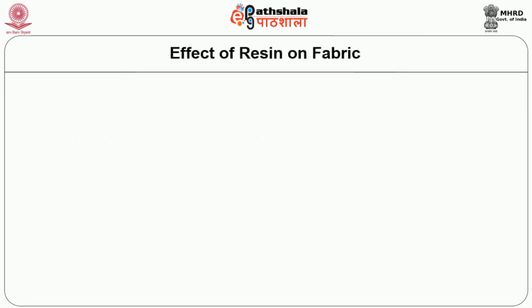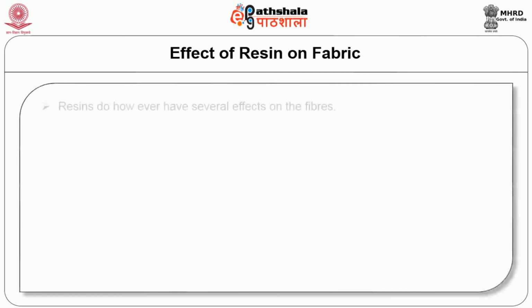The effect of resins on fabric. Resins do, however, have several effects on the fibers. Excessive cross-links cause brittleness, stiffness and harsh feel, giving loss in tear and tensile strength by 30 to 40% and abrasion resistance. Tear strength can be improved by optimum selection of additives and softeners, but it has no improvement on tensile strength.